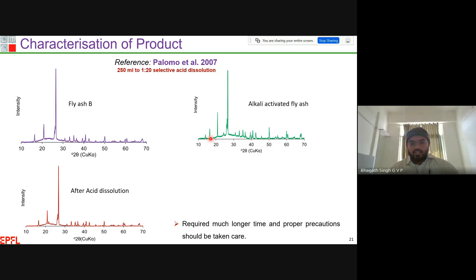And this is the XRD signature of the alkali activated fly ash. You can see the different crystalline phases. I can also see new crystalline phases, one is here and another is here, when compared to the pure fly ash. And along with the broad amorphous hump from 15 to 40 degrees. Here, in the pure fly ash, we have only 15 to 32 degrees.